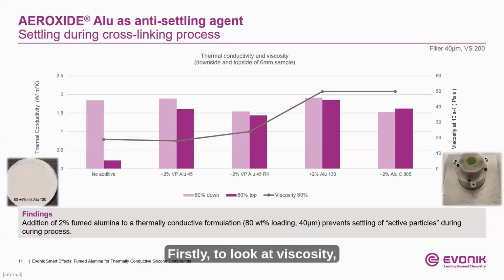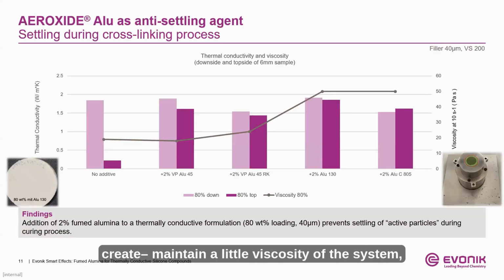Alu-C805. Firstly, to look at viscosity, we again see the same trend related to higher overall viscosity of the material as a function of increasing specific surface areas. So here you'll see, of course, the higher surface area materials, the Alu-C being 100 meters squared per gram and the Alu-130 being 130 meters squared per gram, of course, give the highest viscosity. Again, as the 45s have a much lower specific surface area and are basically created to maintain a low viscosity of the system, they're much more on par with the blank, the spherical alumina only sample without any fumed alumina added. They have very similar viscosities here.